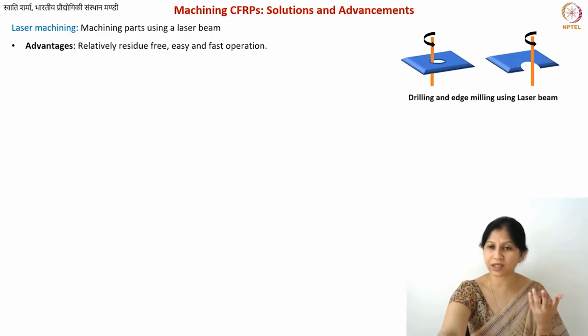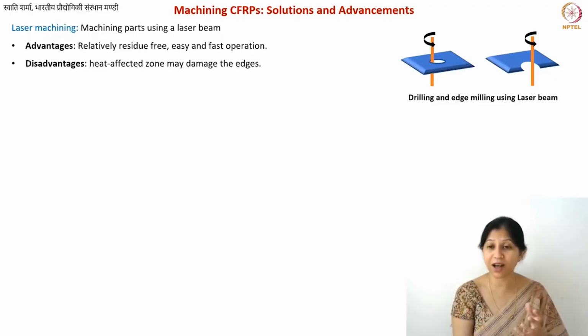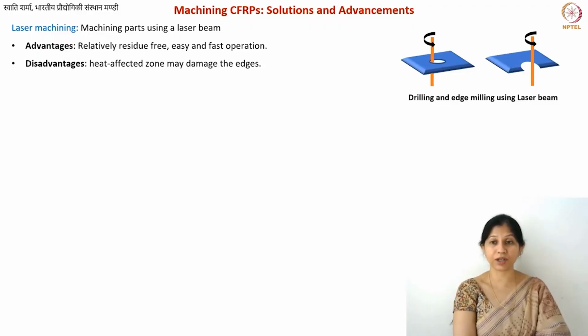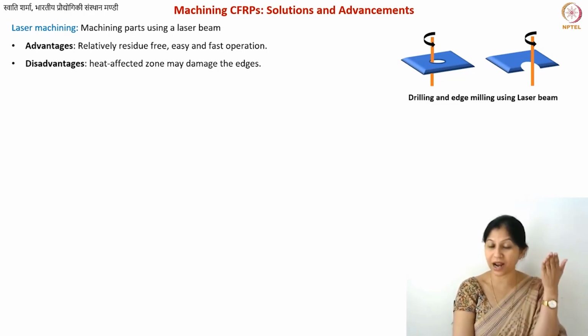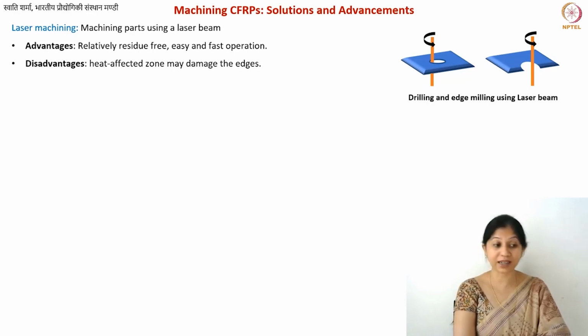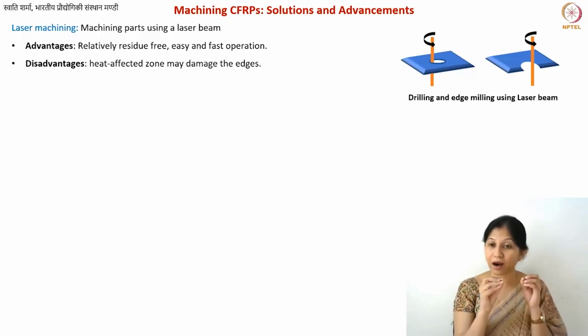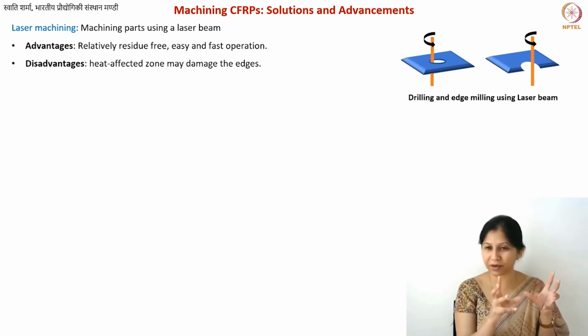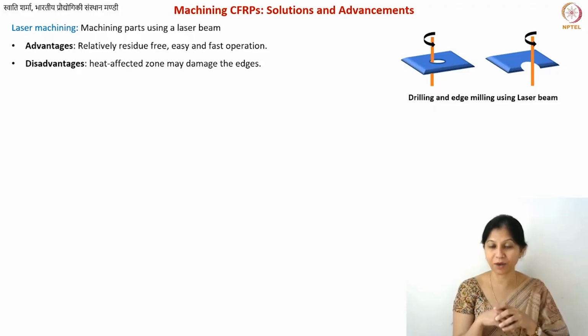What are the advantages? Laser machining is a very commonly available technique in industry nowadays. It is also relatively residue free, and it is a relatively fast operation. However, you also have the disadvantage of heat affected zones. When you are cutting something with a laser, you are melting the material, you are actually generating heat. And as I told you, the thermal properties of your plastic and carbon fibers are very different. So it is difficult to optimize the laser parameters to cut the entire structure uniformly. Laser parameters required for removing the carbon fiber might be too harsh for the polymer, for the resin, and you may end up degrading some of it. So you will have what is known as a heat affected zone. That is a common problem with laser machining of CFRPs.